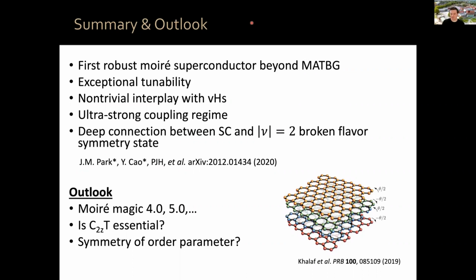So we have measured the resistance to higher temperatures above the transition temperature, actually to pretty high temperature. The system exhibits also a linear-in-temperature resistivity similar to magic angle twisted bilayer graphene, which is reminiscent of strange metal behavior. The origin of that linear-in-T resistivity is not well understood in magic angle twisted bilayer graphene, of course much less in this system, okay? Initially, some people thought that might be related to phonons. Now it seems that phonons cannot explain the story and people are talking about magnetic fluctuations and excitations, okay? It still very much remains to be understood. We have done a little bit of measurement, but again, this is the first report and we still need to do many more experiments in this system.